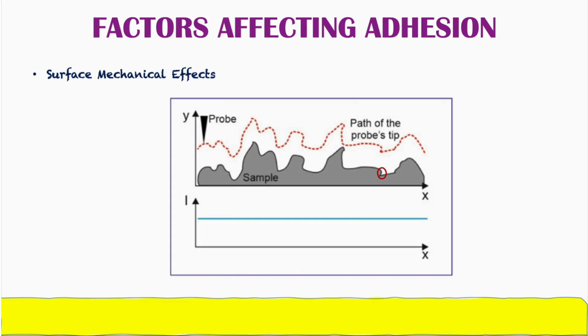Sometimes such areas are even deeper. This is the simplest example I have taken here. We have more complicated, curvy areas which the coating is not able to reach or penetrate, so those areas do not get the coating layer above them. In these cases, when water permeates through the film, there will be areas of contact of water with the uncovered substrate. Uncovered means the substrate surface which could not be covered by the coating due to these tricky roughness areas. This can be a major problem, especially if the coating's role is to prevent corrosion.